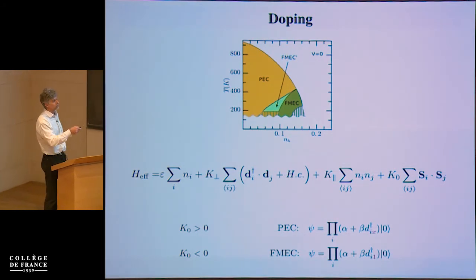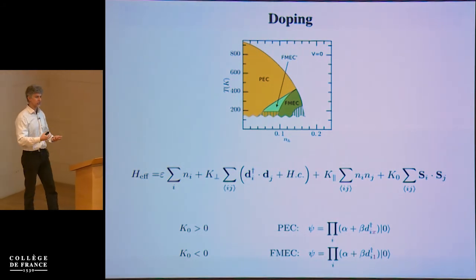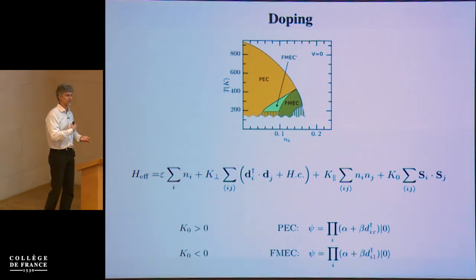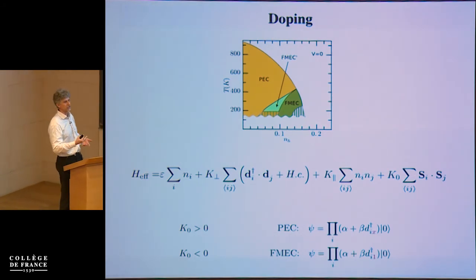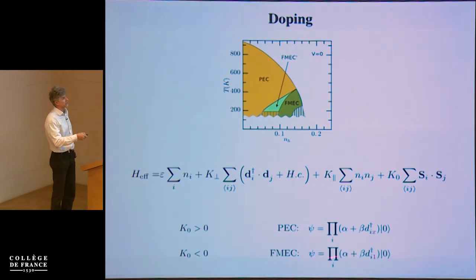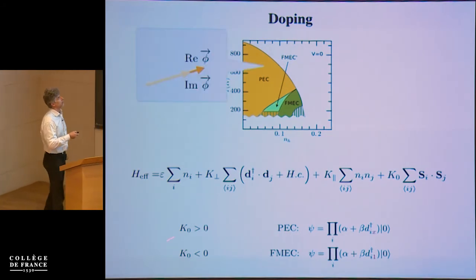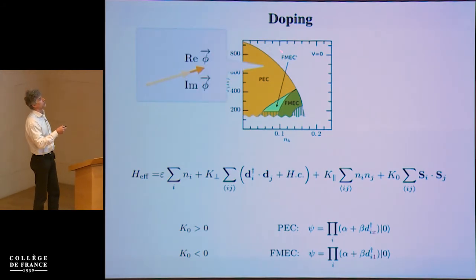While if we dope, we induce, through essentially a Zener double exchange mechanism, a ferromagnetic exchange, and in that case, the ferromagnetic condensate is favored, in which a boson which carries a large spin projection in some direction condenses. So if we look at this phase in our geometrical representation...